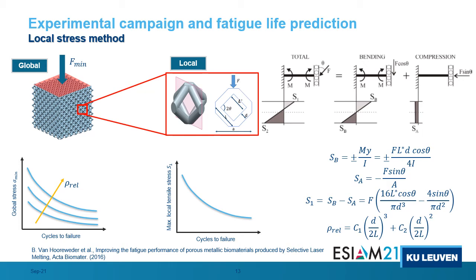Considering the Gibson-Ashby relation between the strut diameter and the metal lattice structure relative density, it is possible to obtain a single SN curve that is not influenced by the relative density, but only by the material condition and by the surface condition of the coupons.